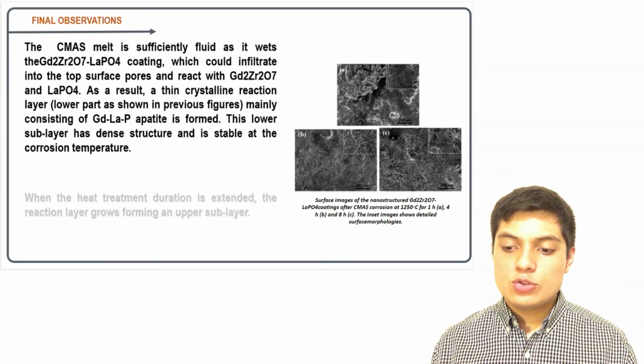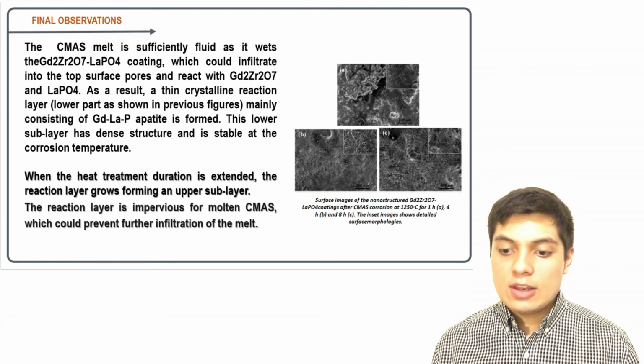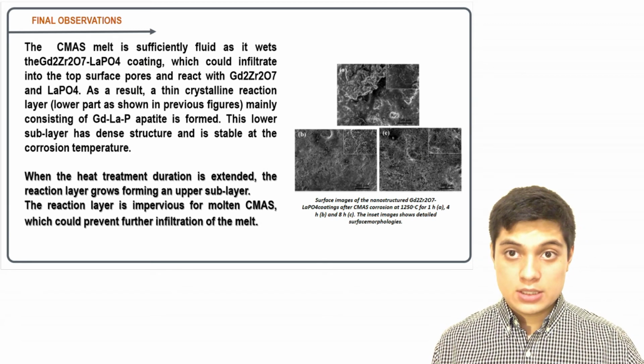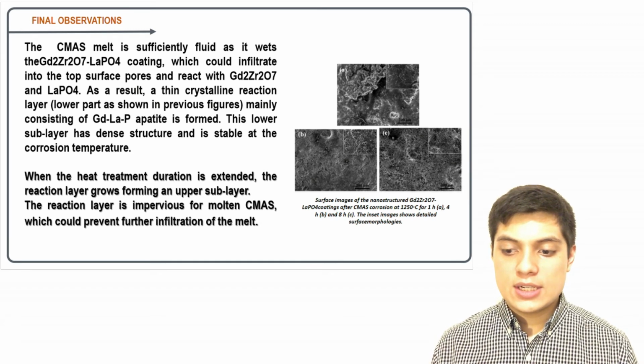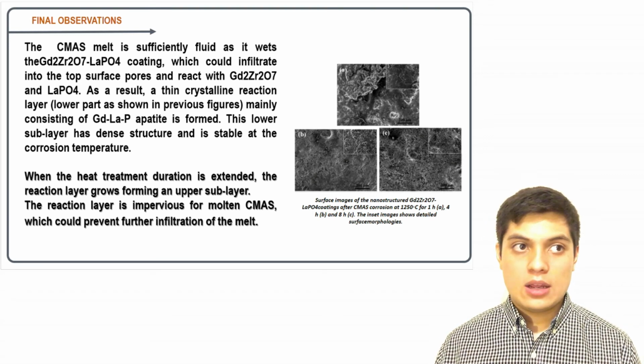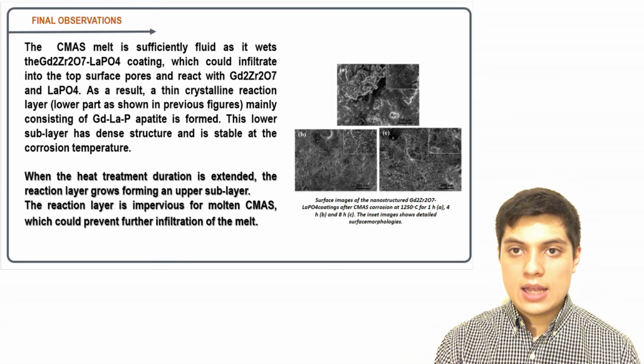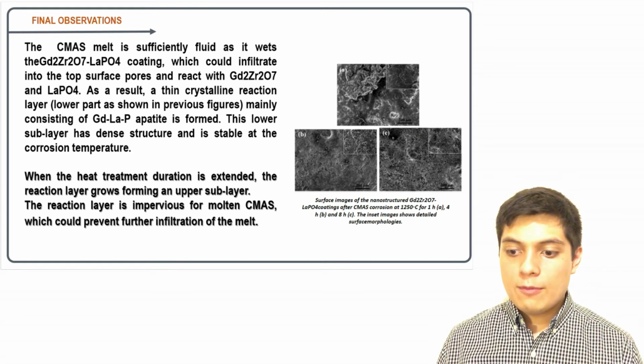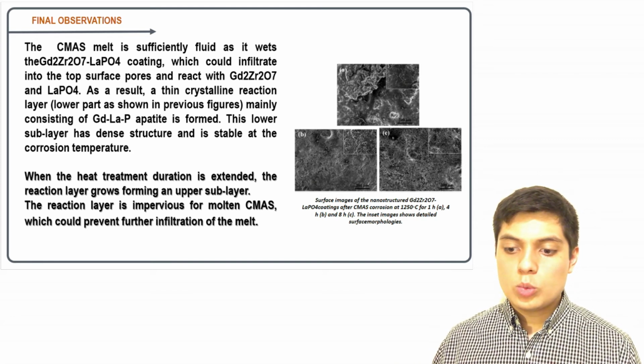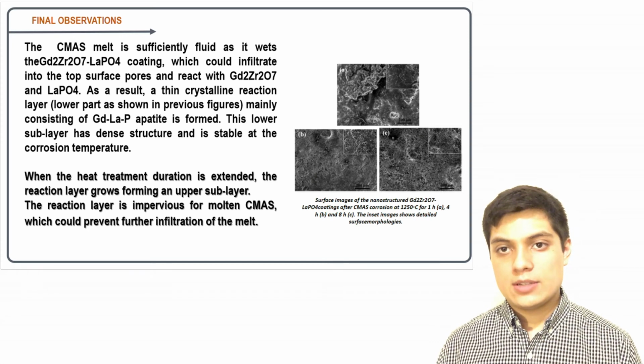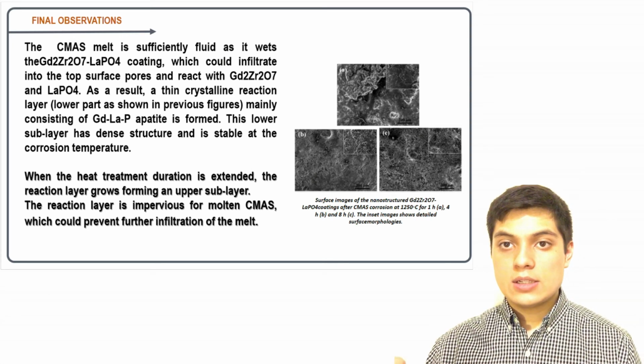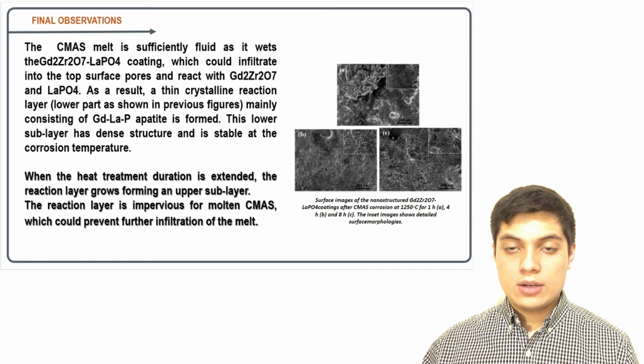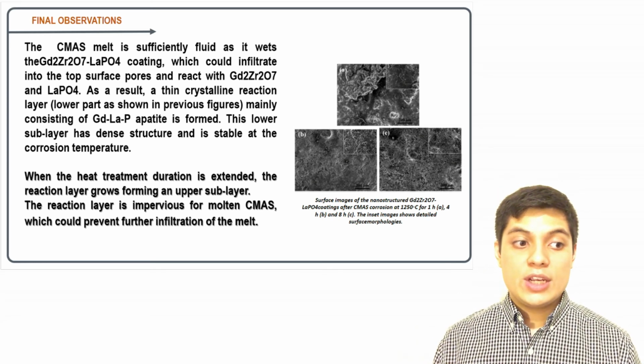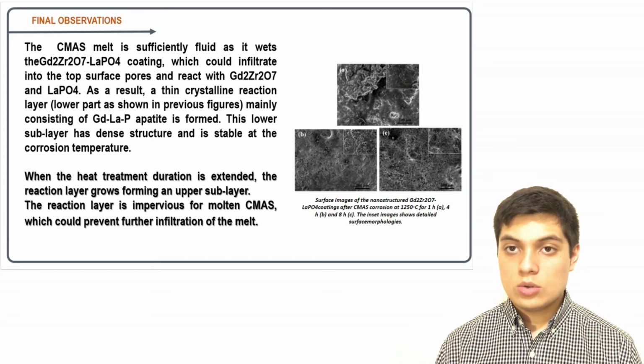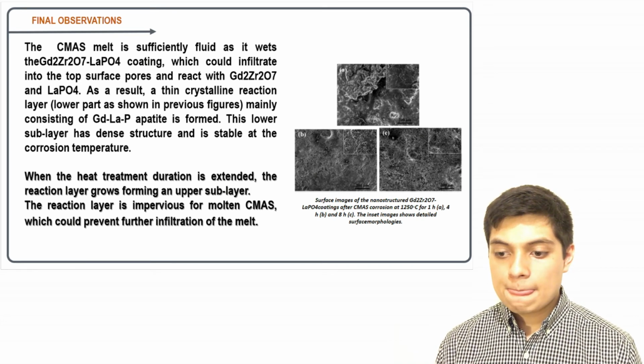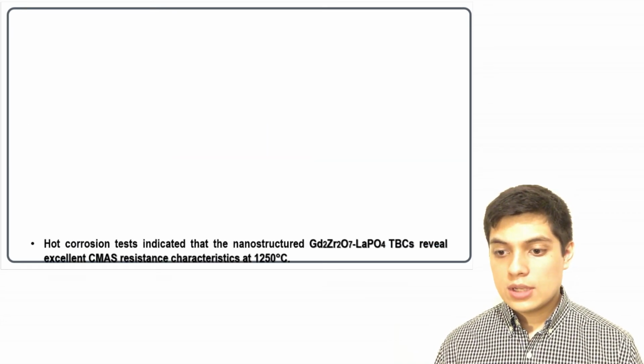So when the heat treatment duration is extended, the reaction layer grows, forming an upper sublayer, and the reaction layer is impervious, so that means that no further penetration of the molten CMAS could happen, which could prevent further infiltration. So this means that the surrounding particles of the lanthanum phosphate create even more resistance to the penetration of the CMAS. So the final conclusions are the following.